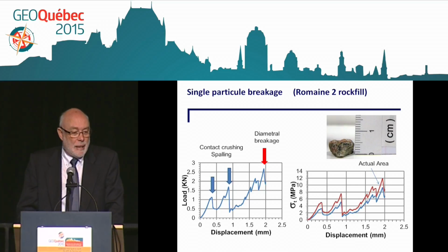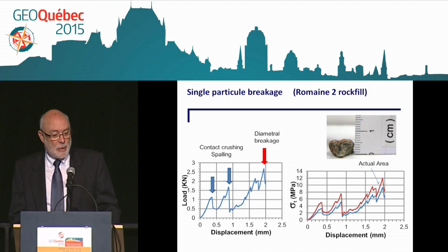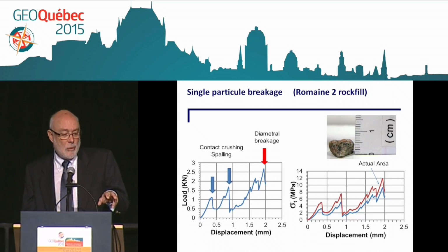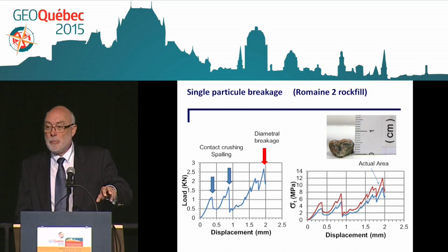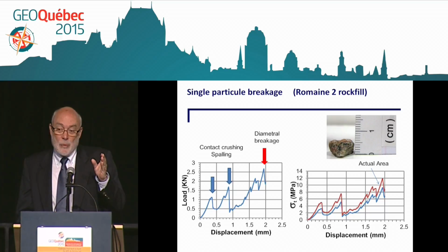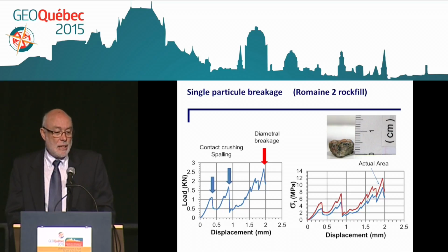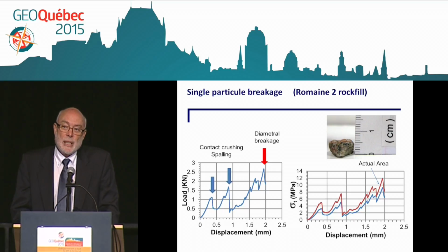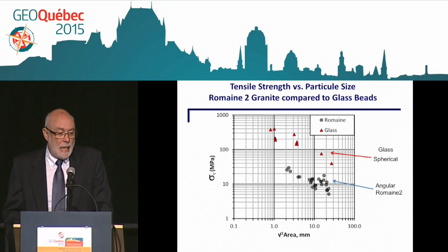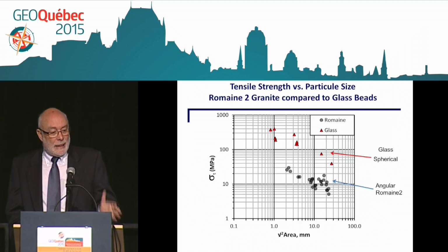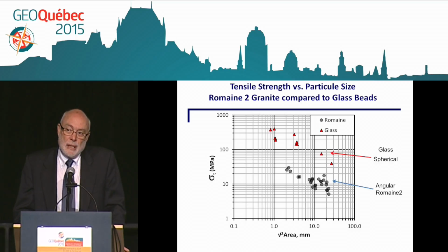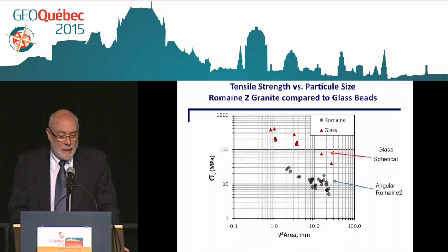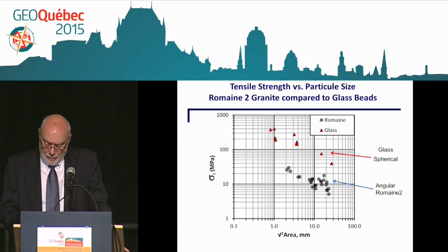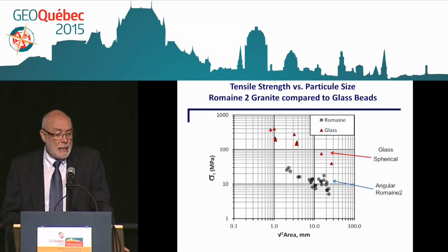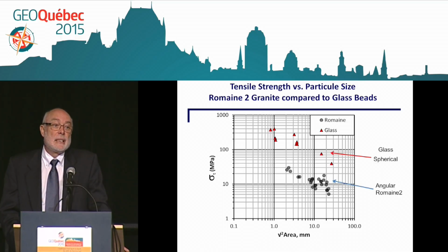This is a typical particle response when it is loaded. The blue arrows show that we get contact crushing, spalling, asperities that go, but when we have the catastrophic failure, it happens like a diametral breakage. This is the load that we take to calculate our tensile strength. And when we look at the results we did on Romaine 2 granite, we see that the strength is increasing as the particle size decreases.